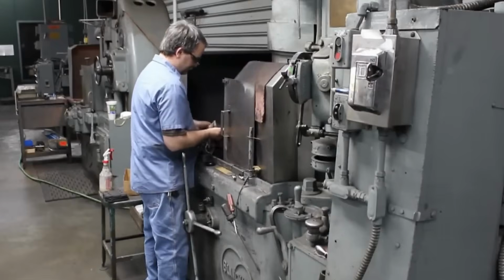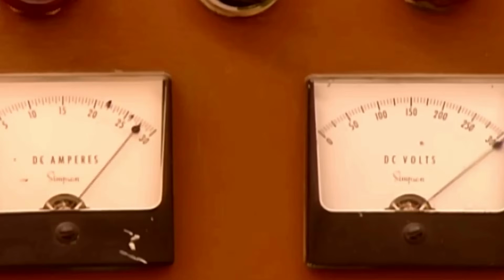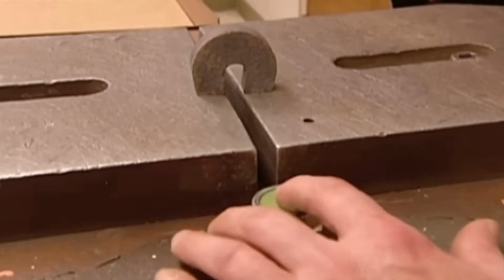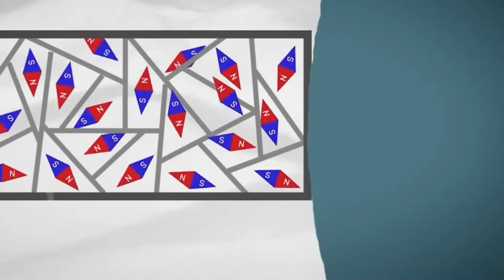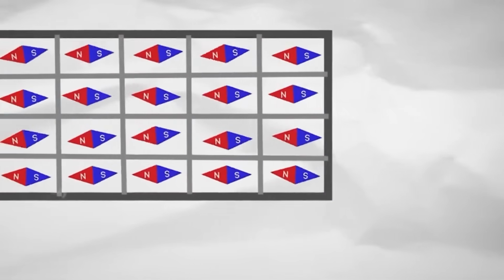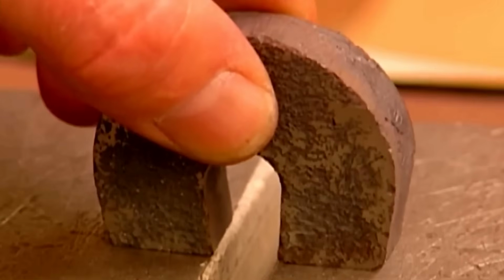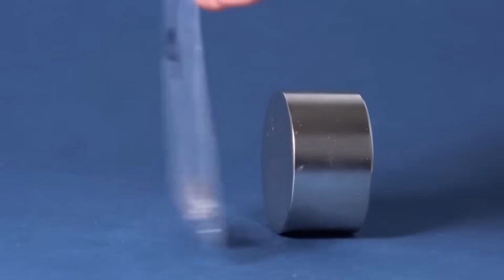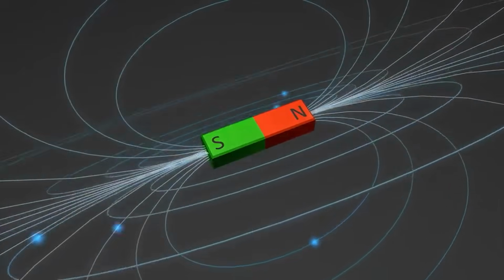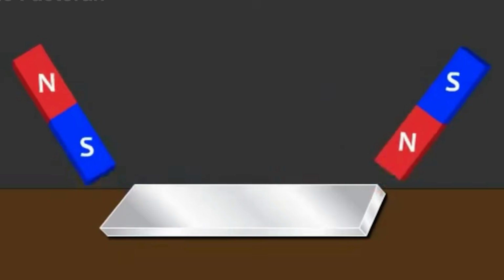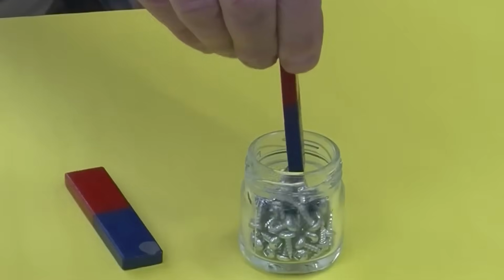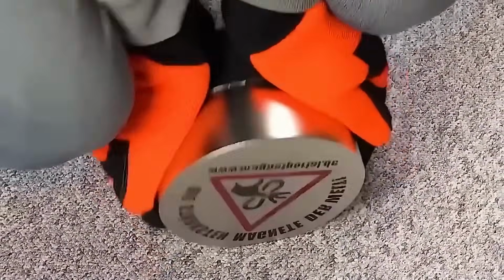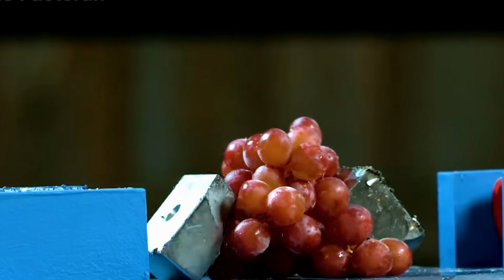Although the pieces are now in their final shape, they're still not magnets. The next step is magnetic alignment. A magnetization coil discharges an extremely intense electrical current for a very brief period, on the order of milliseconds, generating a high-intensity pulsed magnetic field exceeding 3 Tesla. This pulse forces all the internal magnetic domains to align in the same direction. Because it's a permanent magnet material, it retains that orientation indefinitely, unless exposed to intense heat or an equally powerful opposing field. After magnetization, the magnet is fully functional but must be handled with extreme care. Its force can attract metal objects suddenly and dangerously.